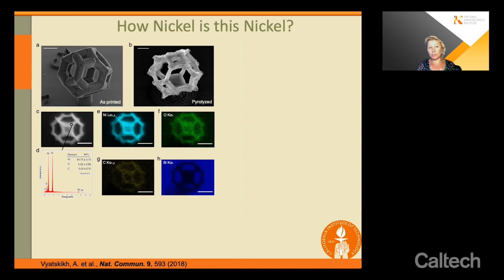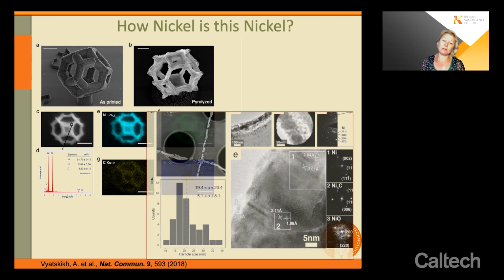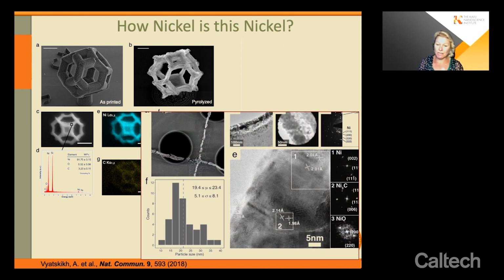Now, the question, of course, is, well, how nickel is this nickel? So we performed a full suite of chemical and microstructural characterization. What I'm showing you here are transmission electron microscope images that show exactly what is present in this material. And it looks like it's pretty much all nickel with a little bit of nickel carbide and nickel oxide that most likely formed after this process. So it looks like we're able to make metals, very, very small nano-architected metals, just by simply using chemical synthesis.